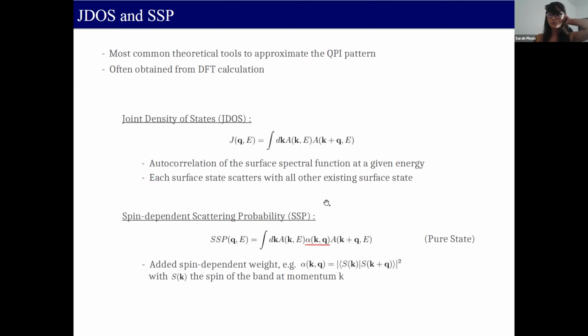Now, the SSP is a correction to the JDOS, actually. It's called the spin-dependent scattering probability. This is the equation that we have for a pure state. It's a bit different for a mixed state. Comparing to the JDOS, we add this new parameter alpha, which is a spin-dependent weight. This is one way of defining alpha. For example, we can define it like this, where S of k represents the spin of the state at momentum k. So in this case, if the spin of the state at momentum k and the one at momentum k plus q are anti-aligned, then alpha equals 0 and the SSP is equal to 0. So this means that we have no scattering between states that have opposite spins. And conversely, if the spins are aligned, then alpha is maximal and we have full scattering.